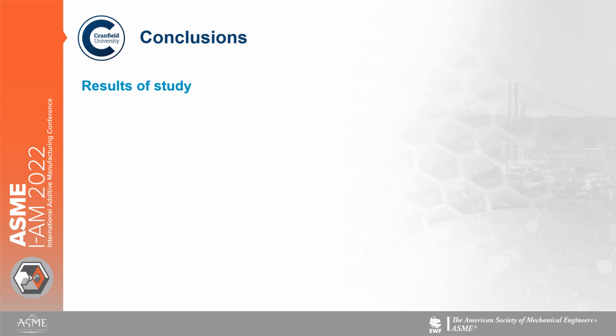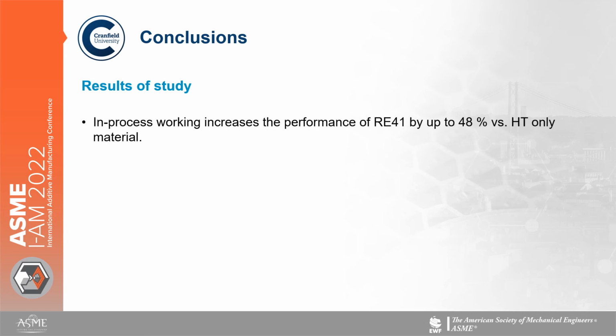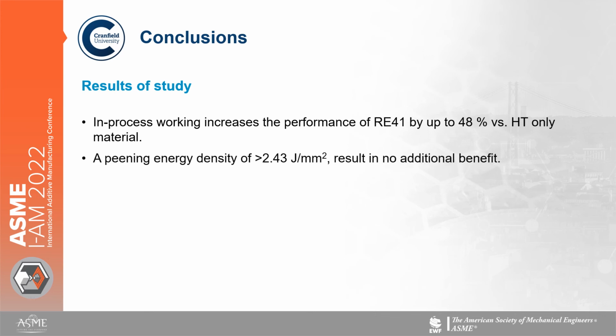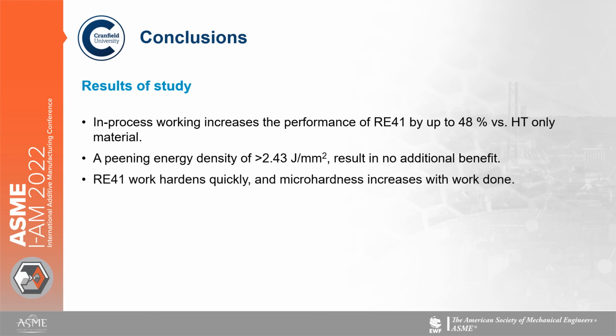So in conclusion, we have the following results for our study. The in-process working increases the performance of Rene 41 by up to 48% versus just the heat-treated only material. And a peening energy density of more than 2.43 joules per millimeter squared doesn't result in any significant benefit for us. We also found that Rene 41 work hardens quickly, and the micro hardness increases with the work done, which can be seen in the paper.